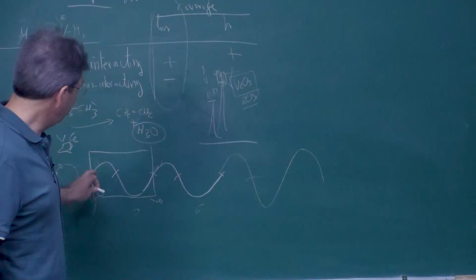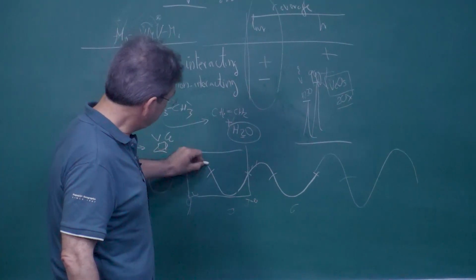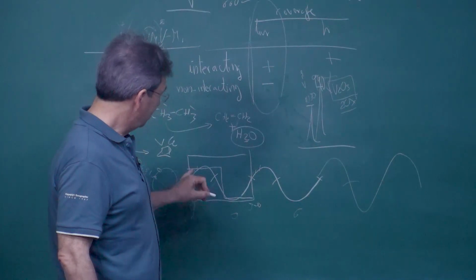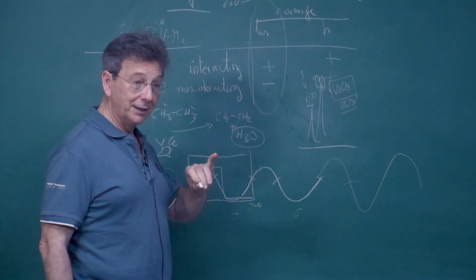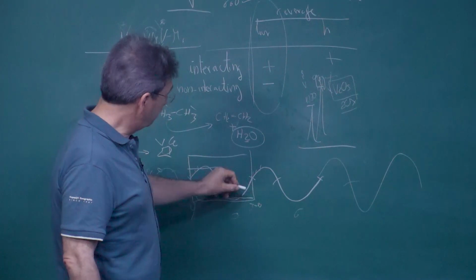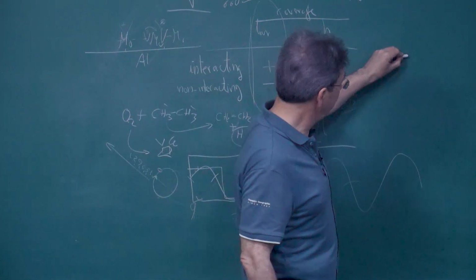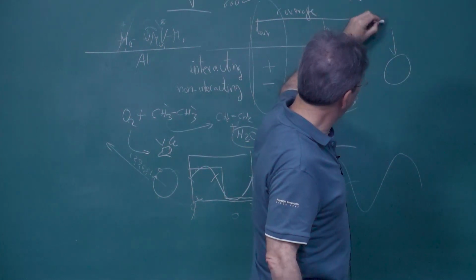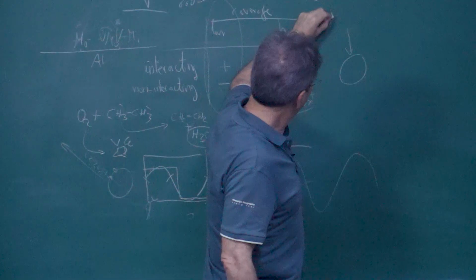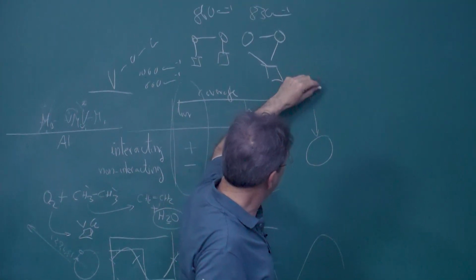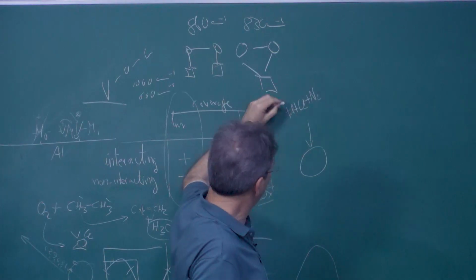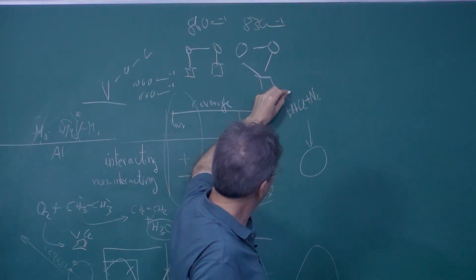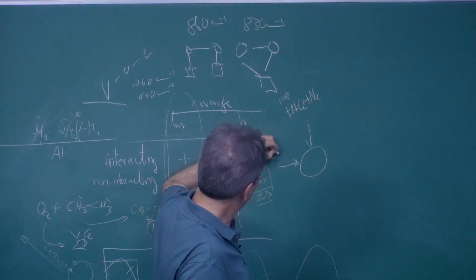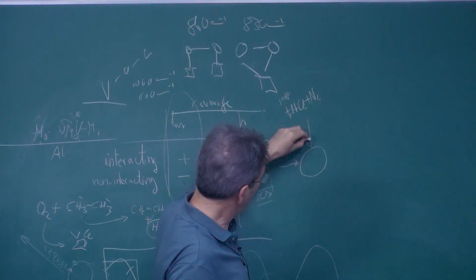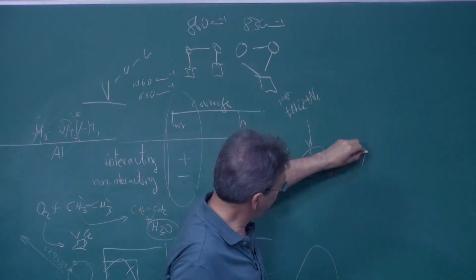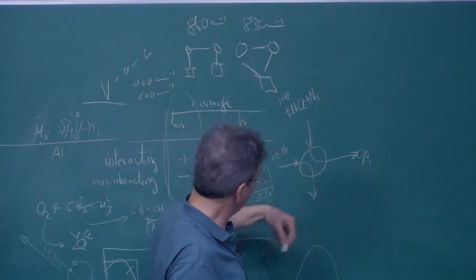Mathematically, this is the typical perturbation that they do. But even if you make a square wave perturbation, that can be assimilated in the whole process to the other, and that's very convenient, because making a square wave perturbation is very easy. If you have a four-way valve, where you have a flow with a reaction feed, which for instance can be toluene plus oxygen plus nitrogen, like 1000 ppm of toluene. And then you have another flow which is only oxygen and nitrogen. With a four-way valve, you are feeding this to the operando reactor, and you are feeding this to the exhaust.